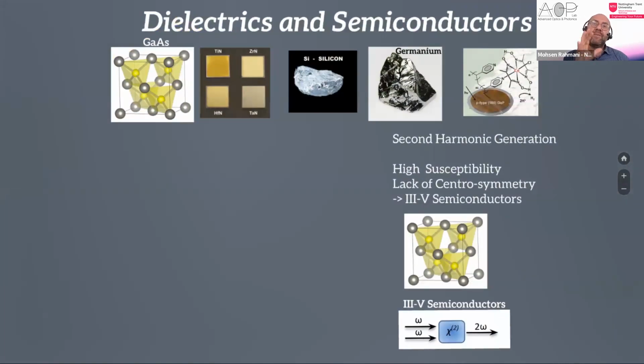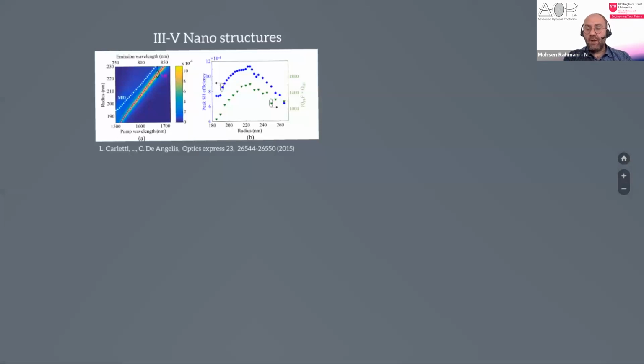So as I mentioned, the main reason of using the dielectric in nonlinear regime is that plasmonics get molten by high laser intensity. So the choice, the plasmonics actually, it's bottlenecked. So we cannot increase the intensity of the laser. That's why people are trying to use different material and use different platform for nonlinear generation. So it has been a very hot area in the last few years, and mostly nonlinear generation with III-V semiconductors, because it has been known for many years that III-V semiconductors, in particular gallium arsenide families, have very high second order susceptibilities. That's why they are very good candidates for generating the nonlinear signal at nanoscale.